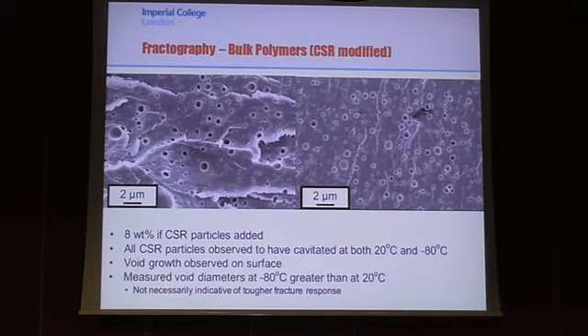And interestingly, the measured void diameters at minus 80 are greater than at 20 degrees. So why is my material not tougher at minus 80 degrees than at 20 degrees? This is not necessarily indicative of a tougher fracture response, because while the work done to grow one void is equal to the integral of sigma dot epsilon, the actual size of the plastic zone is much smaller because we have a much higher yield strength, and that's proportional to 1 over sigma squared. So with the higher yield strength, we end up with a less tough CSR material.